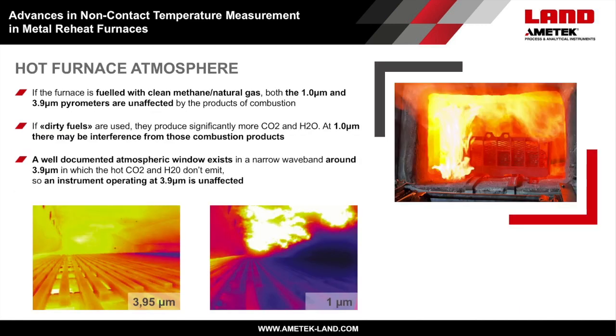Another important influence to the temperature measurements in reheat furnaces is the fuel which is used. If a furnace is fueled with clean methane natural gas, usually a 1 micron thermal imaging system is used, while a 3.9 micron system is also unaffected by the products of combustion, hot combustion gases. If dirty fuels are used, they produce significantly more CO2 and water. At 1 micron, there may be interferences from those combustion products.